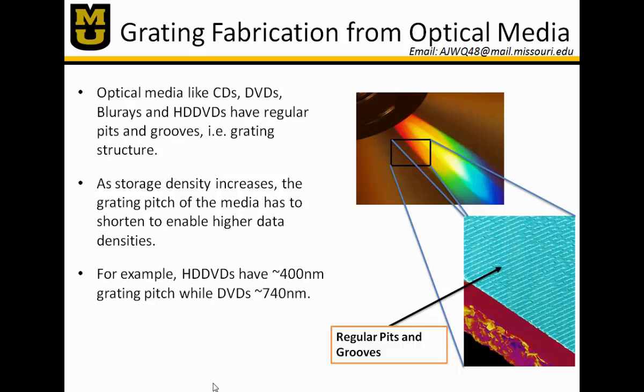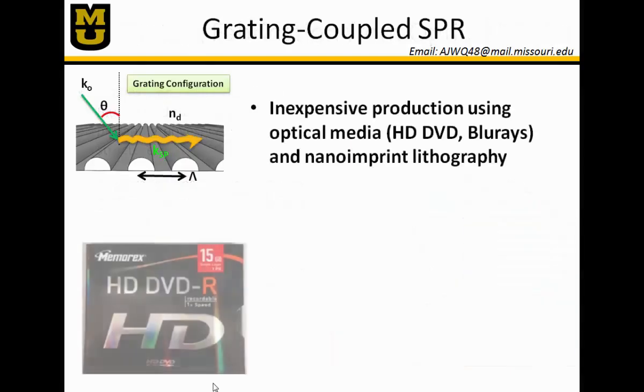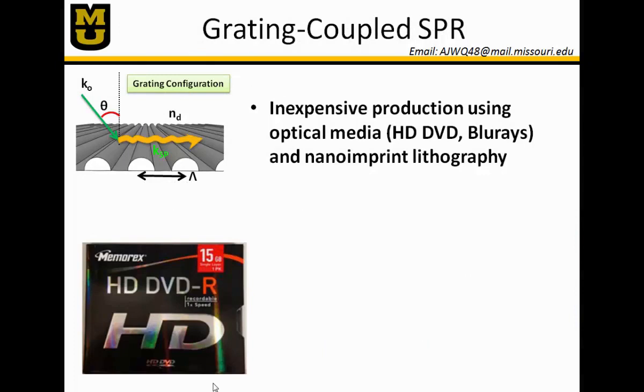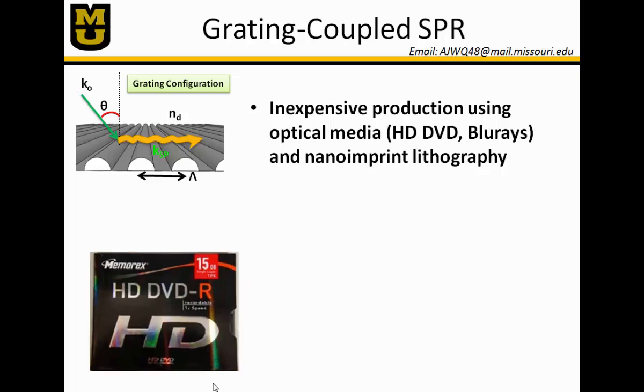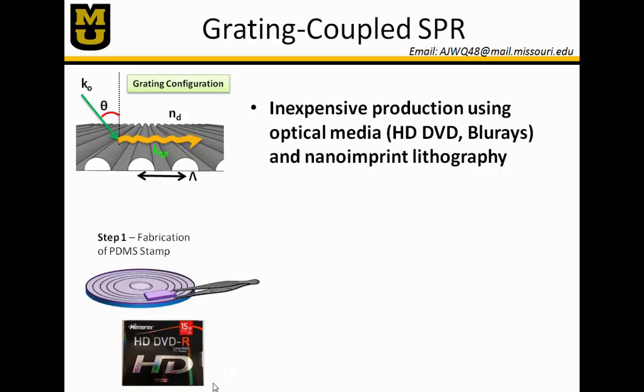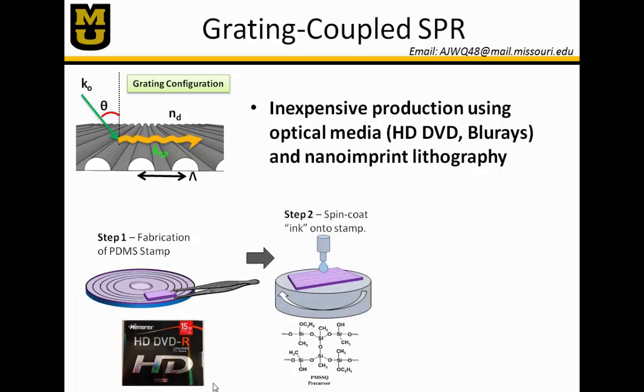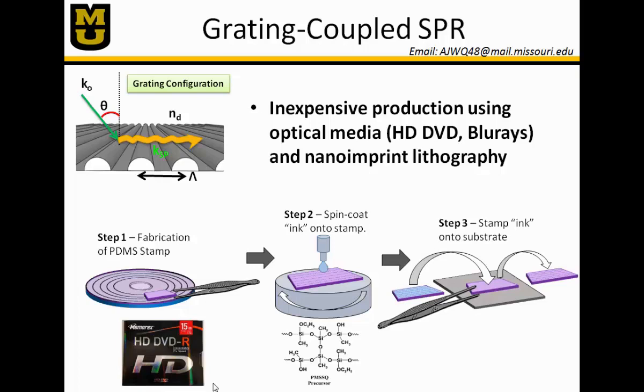So using these gratings, we can inexpensively produce these nanoscale gratings by replicating HD-DVD gratings in polymers. So the way we've done that is through nanoimprint lithography, which can be divided into 3 general steps. The first step being the fabrication of your PDMS stamp. So you can split your HD-DVD in half, expose your polycarbonate gratings, and pour a PDMS polymer on top of those gratings and form a negative image of them. Then, after it's cured, you can spin coat this rapidly curing ink polymer, or polymethylsilsesquioxane, or PMSSQ. And after you spin coat it on that surface, you can stamp it or put it in contact with a silicon wafer or a glass slide. And when you peel off this PDMS, you leave behind a perfect positive image of that HD-DVD in PMSSQ.